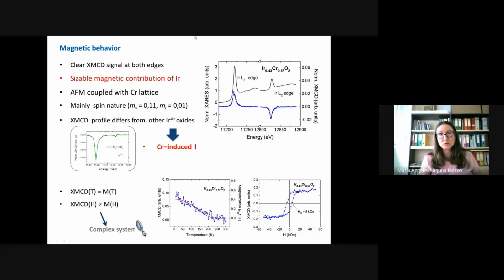The XMCD technique allows us to disentangle the contributions from the chromium and iridium sublattices. The XMCD signal recorded for the iridium edges reveals a sizable magnetic moment on the iridium ions. In addition, the fact that the signal recorded at both L2 and L3 edges is similar in size but with opposite sign indicates that the character of the magnetic moment is mainly a spin moment.